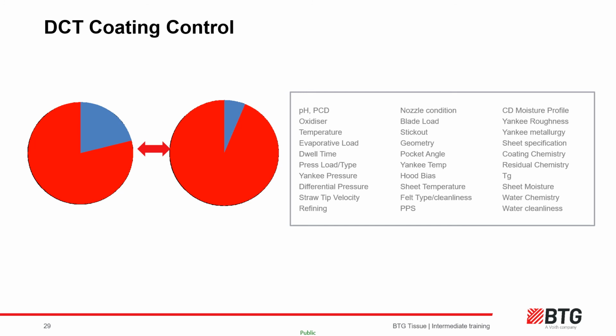If the solid's equilibrium, hence the Yankee coating contamination factor, flips back suddenly or gets worse, this will likely affect coating, unless of course there is online instrumentation to pick up these changes in whitewater stability or total solids quickly to enable a proactive correction or coating changes in advance. Provided we can avoid these flips, then most coating products these days, once set up, are pretty robust.